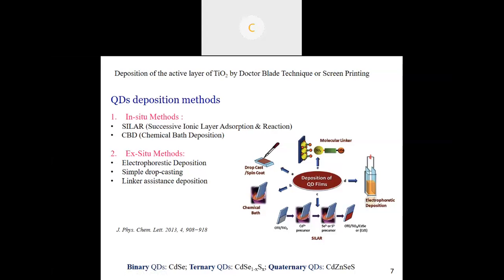Ma'am, then what is the difference between this dip coating and your CBD method? What is the difference between the two? Okay, this is precursor solution. They are all pretty much of the same kind. In the CBD method, you have the precursor solutions together. You stir it at a particular temperature. You keep your films immersed for a really long time, and the reaction keeps happening inside the beaker where you have your films. So there also, after a certain point of time, you have the quantum dots growing on it.